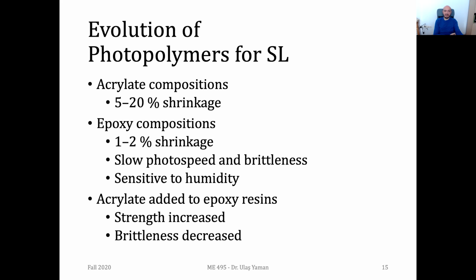And the problem of the epoxy composition is that you need to spend more time on curing. You cannot cure it using a very high-speed technology. You should be curing it slowly, and that takes lots of time. Another issue is that the cured products have high brittleness, and this is again not preferred in stereolithography. We don't want brittle products. The last issue is that the epoxy compositions are very sensitive to high humidity levels, and their properties change a lot once you have humidity around.